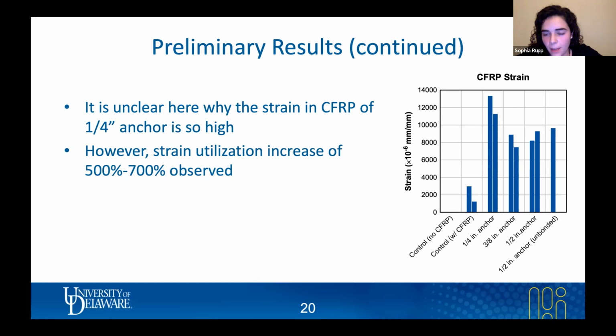Yes, I'd say that. And another takeaway from that is, as the strain increases, it's also indicating that you're getting more use out of the material itself. And that's one of the great things about the anchors: compared to an unanchored beam, you get a higher increase in the strain and you get more use out of the properties of the material. So not only the increase in ductility, but also more use out of the material.